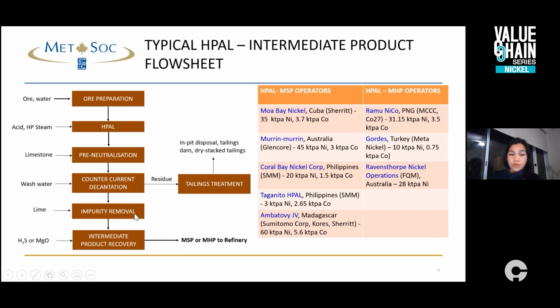So basically the virtually impurity-free pregnant liquor solution is sent into an intermediate product recovery, where nickel and cobalt are dropped out of the solution and precipitated into a solid form by the addition of hydrogen sulfide gas. So you will produce your mixed sulfide product, or you can add magnesia slurry to produce mixed hydroxide product. These intermediate products are the ones that are sent to a downstream refinery to either refine into a class 1 metal or straight into nickel sulfate crystals.